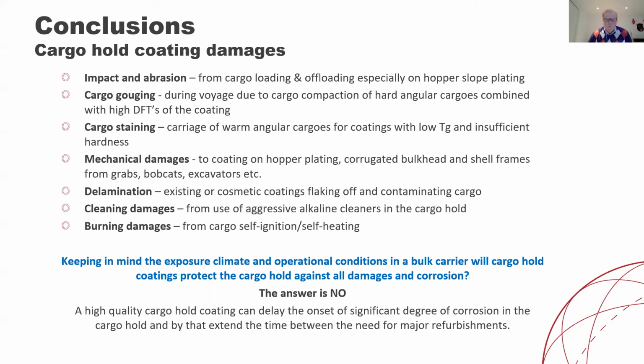You have mechanical damages, as I mentioned. You have delamination, like cosmetic coatings that can then create contamination of the subsequent cargo that is carried. You have cleaning damages, as mentioned also, if you use very aggressive alkaline cleaners or acidic cleaners in the cargo hold and not removing them completely after cleaning. And you can have burning damages from self-ignition or self-heating cargoes.